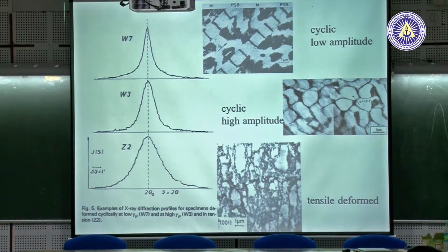Now, in the persistent slip bands, which is this ladder structure, you have dislocation walls in which the dislocations are hammered together to an extremely high dislocation density. All of them are edge dislocations in very strong dipole configuration. The screening is very strong. So you have long tails.